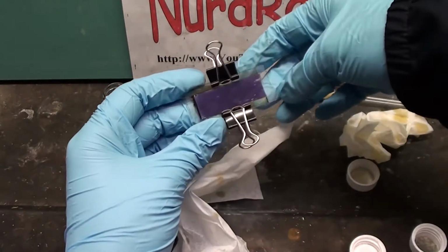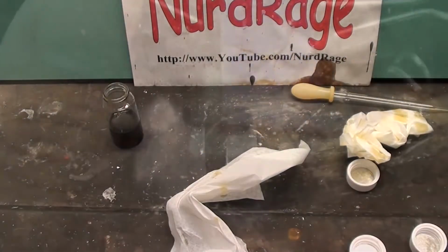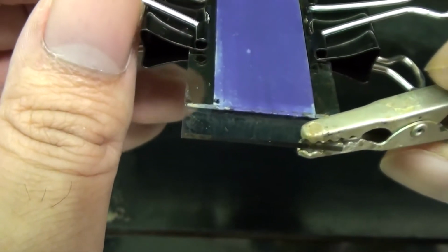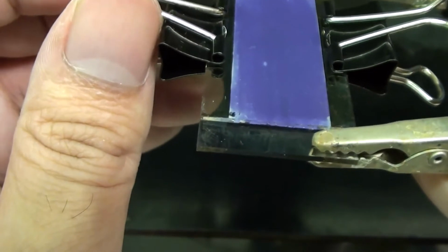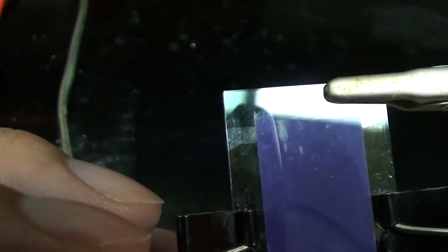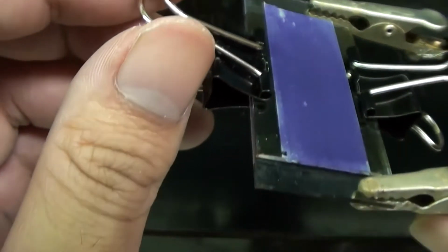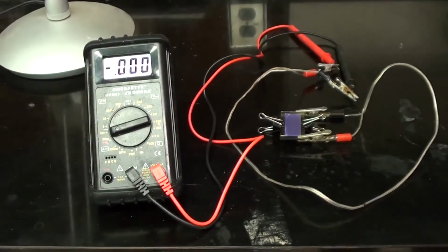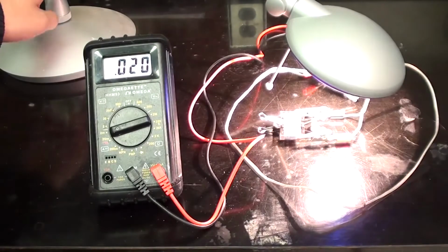And it's done. Now we're going to test it. Using alligator clips, attach ends to the exposed conductive sides of the FTO glass. The titanium dioxide side is the negative side, while the carbon soot is the positive side. Connect the assembly to an appropriate meter and hit it with a very bright light. And look at that!